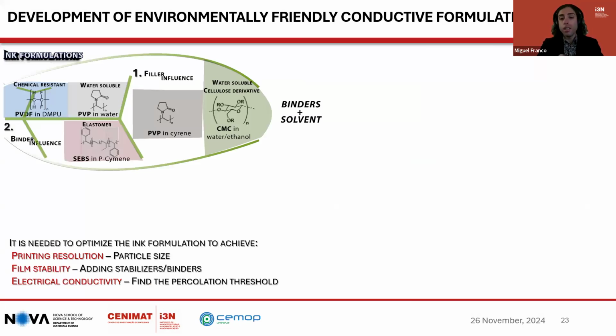When designing the ink, it is needed to optimize the ink formulation. Particle size is a limiting factor of printing resolution. To achieve high resolution, it requires fine opening meshes, and this places stricter particle size limits in order to avoid clogging. In the case of high resolution extruders using small nozzles, the use of, for example, nanoparticle-based inks can be a challenge.